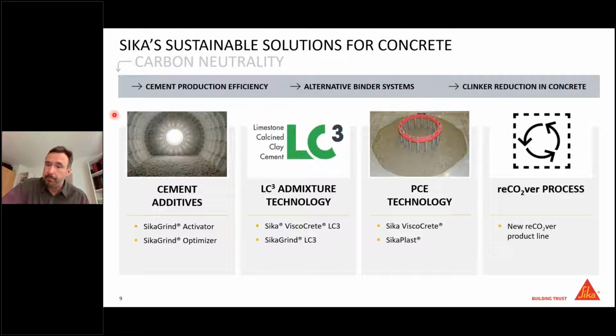And also an interesting recycling process has been just developed by Sika, the so-called reCO2ver process, which consumes CO2 during the recycling process of concrete, and the outcome is actually a high quality aggregate, and at the same time also using all components of concrete, so separating the cement paste from the sand and gravel, allowing for up to 100% recycling rate.